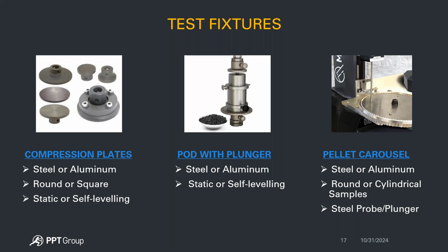Now, one of the requirements here is also, especially when you're testing multiple batches of samples, the recommendation is to have pods or sample fixture assemblies that will allow you to empty the tested samples quickly if you need to go to the next step of the test, which is more of a physical test than anything, where you pour the tested samples into a sieve to see how much of it passes through the sieve. And so having fixtures that allow you to easily discard the tested samples is critical to the testing application. And then I did mention the third type of test, which is the custom type of test.